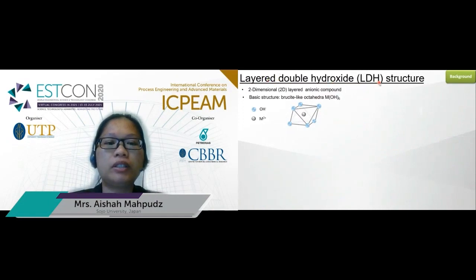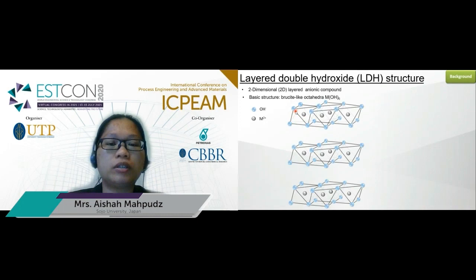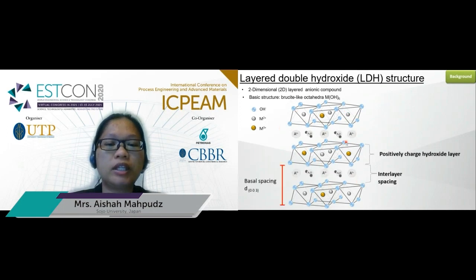Layered double hydroxide, or LDH, is a class of two-dimensional layered anionic compound. Its basic structure is similar to brucite octahedra, in which one metal center is surrounded by 6 hydroxide groups. These edge-sharing octahedra create an infinite hydroxide layer, and for LDH, some of the divalent metals are substituted with a trivalent metal, creating a positively charged layer. To compensate the excess charge, there is an anion occupying the interlamellar space.